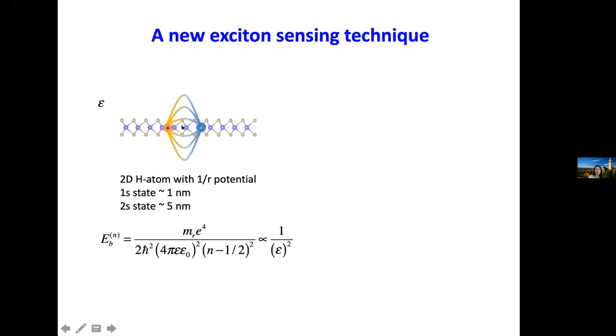I told you that the exciton response from a monolayer semiconductor is very strong. So the electron and hole form a 2D hydrogen atom-like object, and they form a series of Bohr states. So the fundamental state, the 1s, has a Bohr radius of about 1 nanometer. The 2s state has a Bohr radius of 5 nanometers, and the 3s will be bigger. So the bottom line is that for those excited exciton states, the Bohr radius is much bigger than the thickness of the sample. So the field lines are outside the material a lot, and it's very sensitive to whatever is nearby.